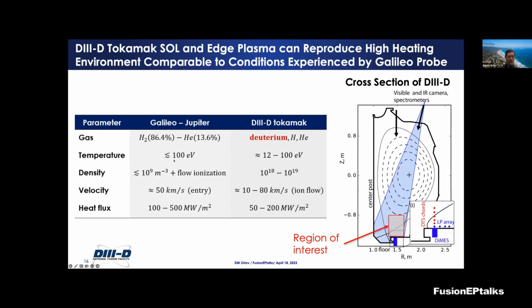The temperatures are about 100 eV in the Galileo Jupiter entry, and they're about 12 to 100 eV at the edge of the plasma in DIII-D.